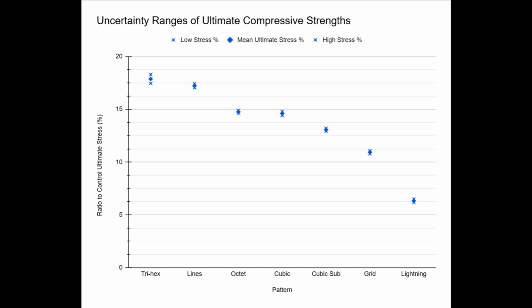This graph shows the expected ranges for each pattern as a percentage of a fully solid part. Our theoretical uncertainty, which would mainly come from the precision of the strain gauge and the accuracy of our calipers, was found to be around 5.1% based on the stress-force equation and our propagations. Most samples had a final uncertainty of roughly 2%, meaning that we were able to narrow the interval with our large sample sizes.